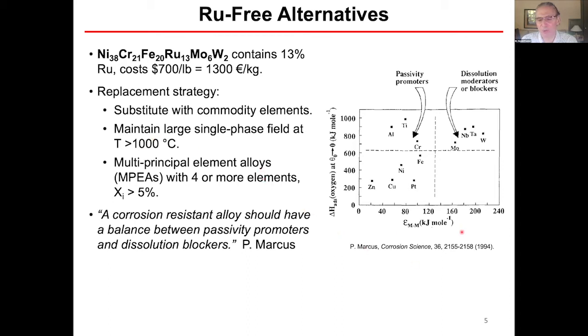And guiding us has been this work from Philippe Marcus that's already quite old, 25 years old, but we think it's quite insightful, where he talks about alloying elements being either passivity promoters or dissolution moderators or blockers. And this is a plot of the adsorption enthalpy for oxygen, oxygen adsorption on the surface. And this is a measure of the metal-metal bond strength. So if we have a high metal-metal bond strength, that might prevent the dissolution from taking place. But if the metal-metal bond strength is low, but let's say the metal oxygen bond strength is high, as we know from these strong oxide formers, that would promote passivity. And Philippe suggests that we should have a balance between those.